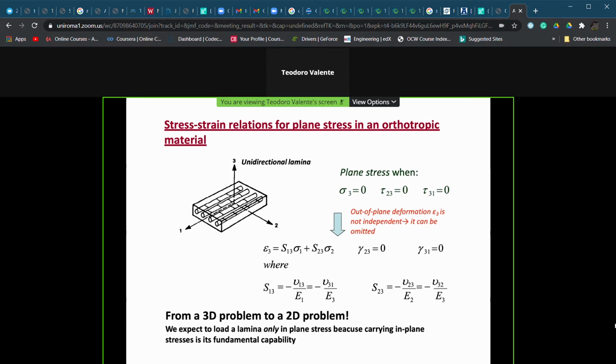Now let's see how this approach can be simplified when we talk about orthotropic materials, which is our case, which can be classified as the basic element of multi-layered composite materials, the lamina. In this case, our hypothesis is a plane stress state, and this means that along the axis number 3, both the normal strains and the shear strains can be put equal to 0. And so our relationship can be further simplified as written here, and we move from a three-dimensional problem, which is a general approach, to a two-dimensional problem.